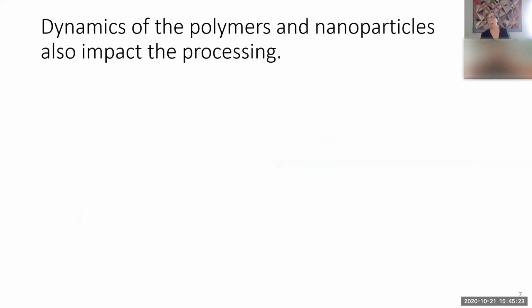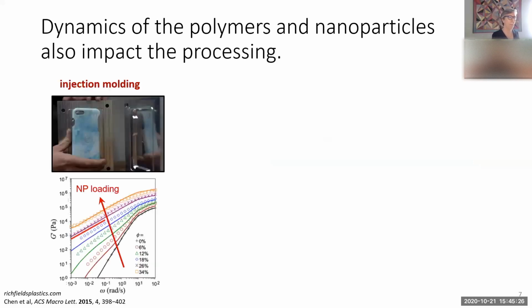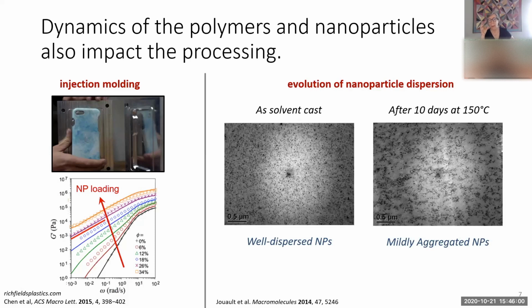So in addition to having dynamics that impact the properties, the dynamics of the polymer and the nanoparticles also impact processing. And perhaps the simplest example is if you add nanoparticles to the system, you go from a very simple viscoelastic liquid, that's the black data here. And as you increase the amount of nanoparticles, you go towards solid-like behavior. And that will impact the ability to injection mold intricate parts. So even if you have remarkable mechanical properties in the nanocomposite, you might still have trouble when you go to process it.